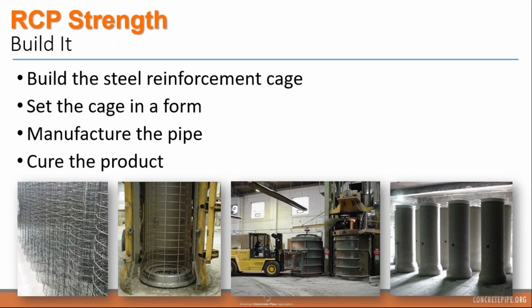And then finally, in the photo on the far right side, the pipe is finished by placing it in a kiln overnight to achieve maximum strength in as short a period of time as we can while helping to minimize shrinkage cracks. Most plants in our industry are going to utilize a steam kiln for this process.